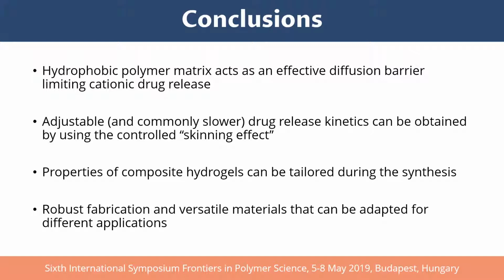Properties of composite hydrogels can be tailored during the synthesis by changing the formulation of the precursor solution, by changing the irradiation type, for example, by using gamma irradiation or electron beam, which eliminates the need for a photoinitiator, or by changing the composition of the non-solvent bath. The fabrication of composite reservoirs is simple, robust, and easy to scale up. Obtained materials are versatile and can be adapted for diverse applications.